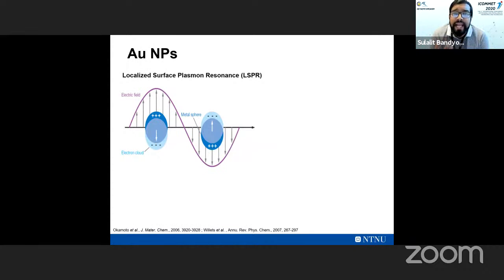So this property is a size-dependent, shape-dependent, solvent-dependent property, meaning if you're able to tune the size, shape, solvent, and other factors, you would be able to tune the performance of these nanoparticles. More importantly, for gold nanoparticles, this happens within the UV visible range, meaning the beautiful color of gold nanoparticles from pink to purple is because of this property, LSPR, and that makes them exciting candidates for optical imaging, etc.